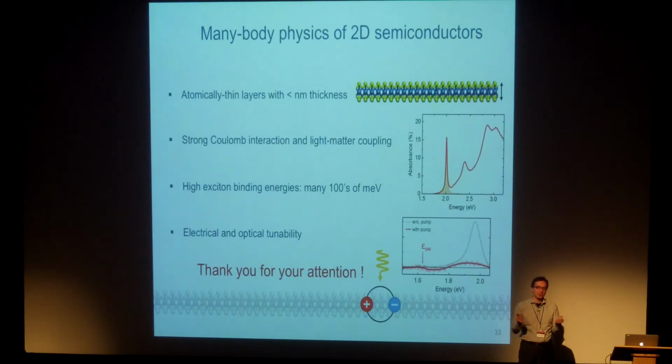Not only because of screening, but also because the interaction is not 1 over R anymore. And there are a lot of questions from us to our theory colleagues on how it will affect this. Well, it's actually not obvious you get an electron hole liquid, because that mostly depends on there being multiple valleys lowering the kinetic energy versus the binding. So it might not work.